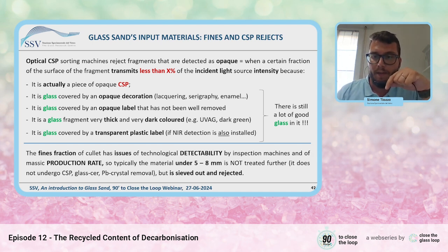And also the machines that reject the ceramic fragments have to shoot compressed air jets against the fragments that are seen by the detector, and they have a certain target size that can be larger than the piece that has to be shot off. So they also shoot some innocent good glass. So what happens is that sometimes even 80% of these CSP, the ceramic rejects, is in fact still good glass, and it is very good to get it back into the loop.